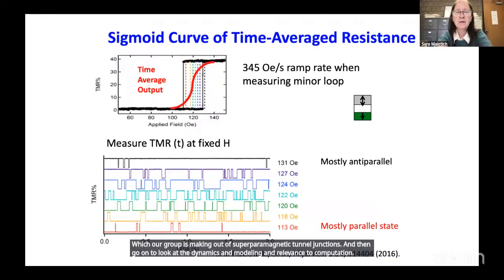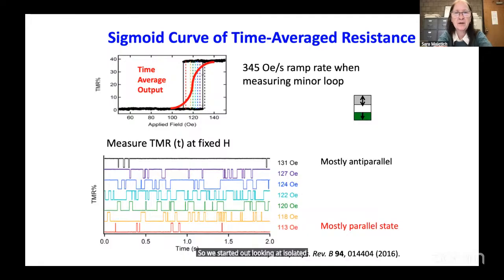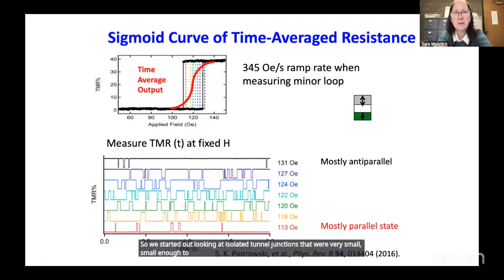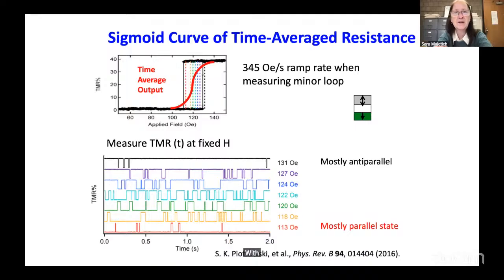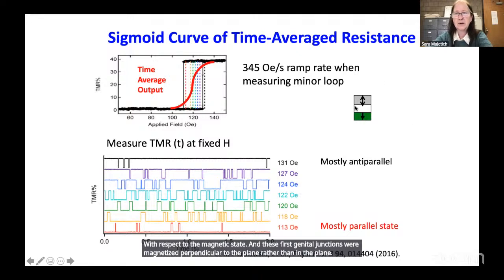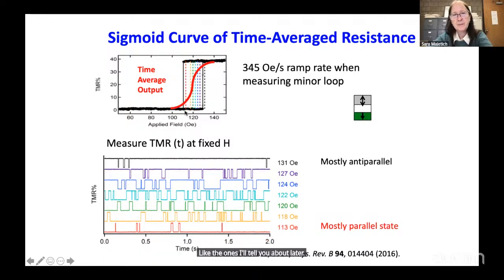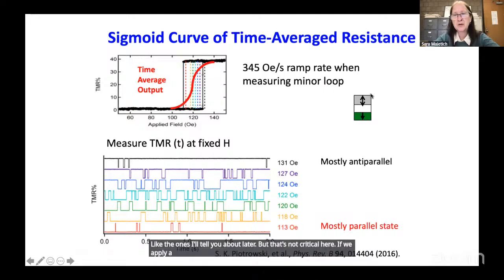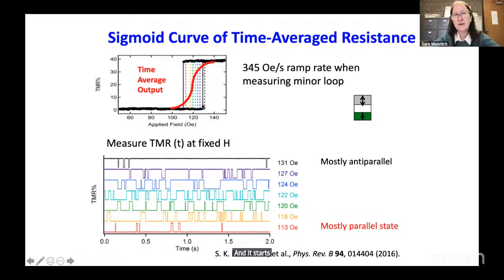So we started out looking at isolated tunnel junctions that were small enough to be thermally unstable with respect to the magnetic state. And these first tunnel junctions were magnetized perpendicular to the plane rather than in the plane, like the ones I'll tell you about later. But that's not critical here. If we apply a magnetic field and measure the electrical resistance through this device, if we ramp the field, we get this black curve, and it starts at one resistance level and suddenly switches up, saturates. If we turn down the saturation field, it switches down very abruptly.